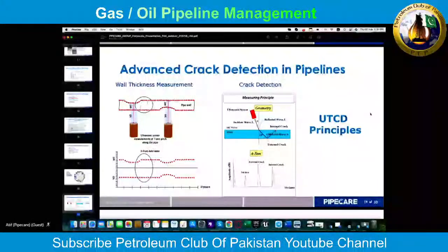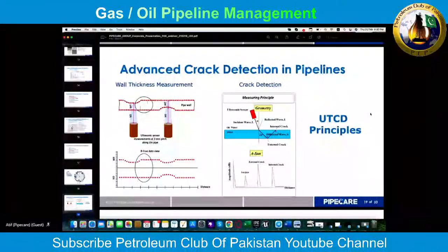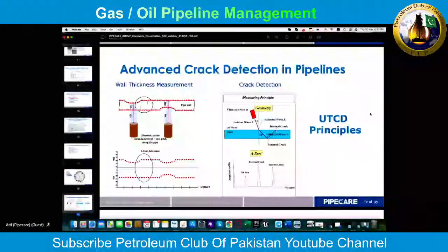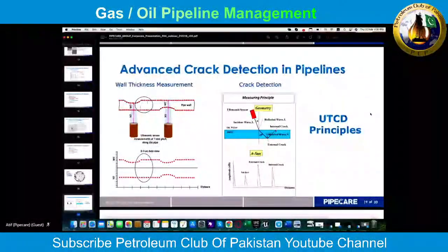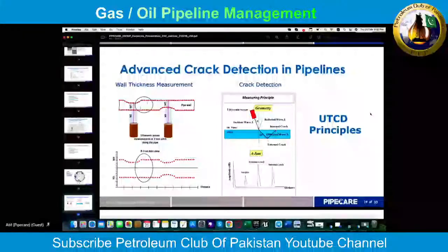And because the tool travels through the pipeline, there's only a limited amount of time that the transducer is over a certain location. So what we see is that the tool records the first 3 echoes, which would give it the internal surface, the external surface, and the internal surface, so that internal cracks as well as external cracks can be detected. Next, please.